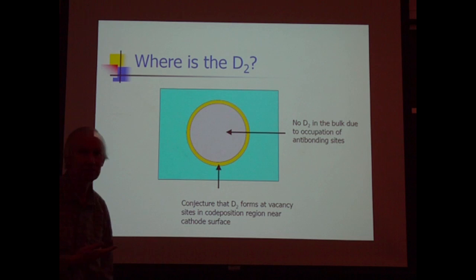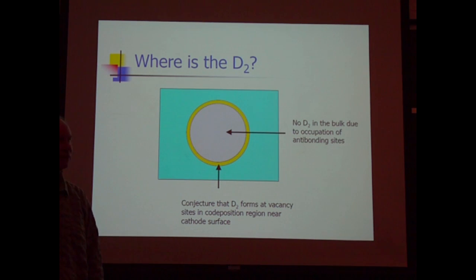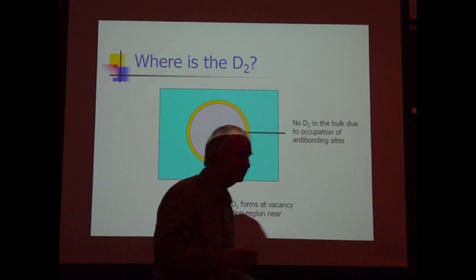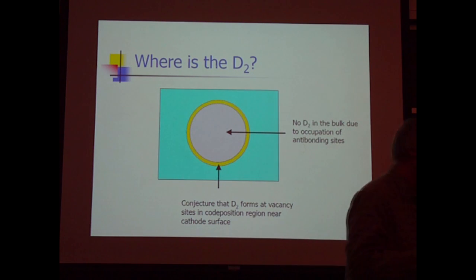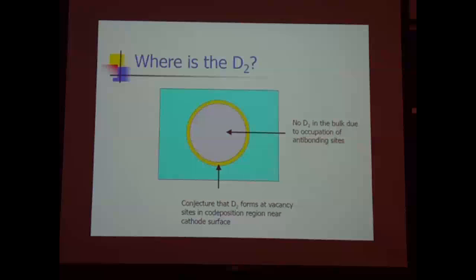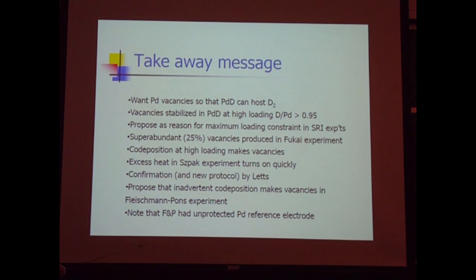In Fleischmann and Pons experiments, uncontrolled, and all negative experiments didn't reach the 0.95, so you can't make the vacancies. In the positive experiments, except for the Szpak experiment with the Letts protocol, vacancy formation is uncontrolled. In Mitchell's electrochemical experiments, vacancy formation is uncontrolled, but on the other hand, if you make your spiral, then according to me, that gives you the chance of having the local strain energy aid in making vacancies easy to form. The takeaway message: I want palladium vacancies to host D2. Stabilize them above 0.95 in palladium, above 0.67 or something in nickel.